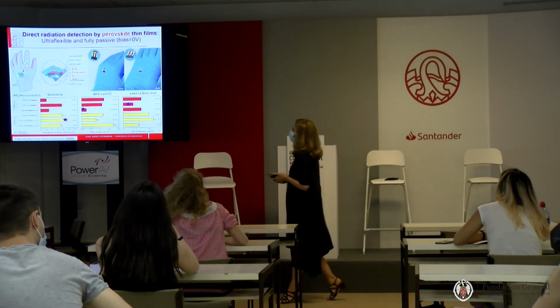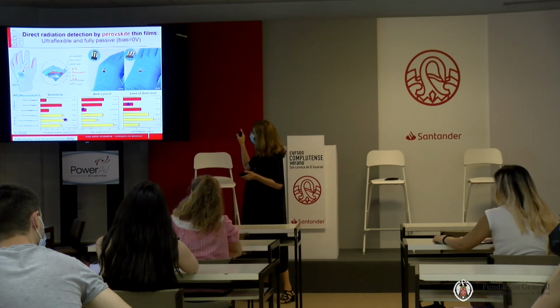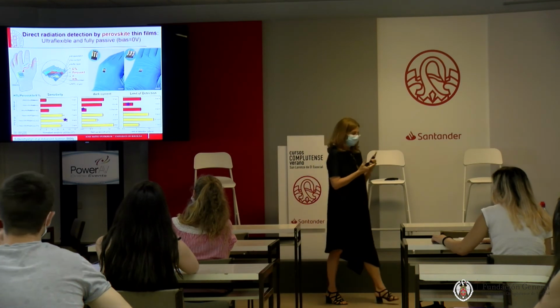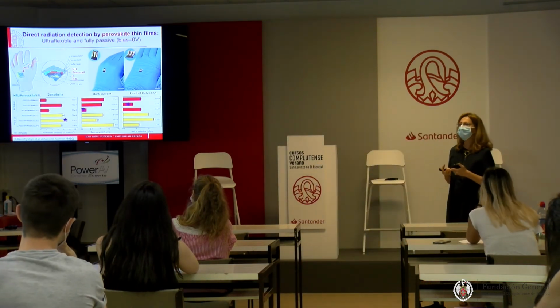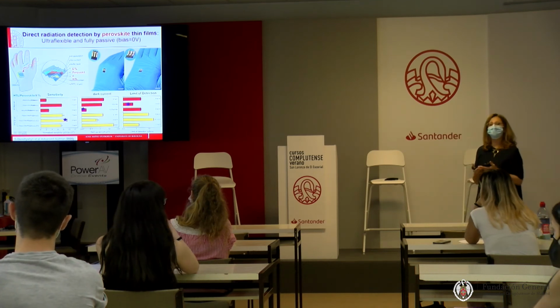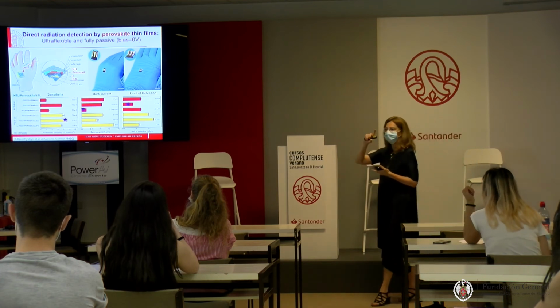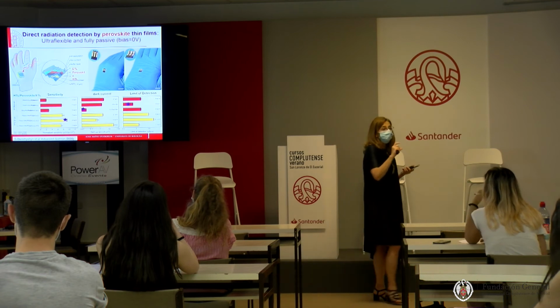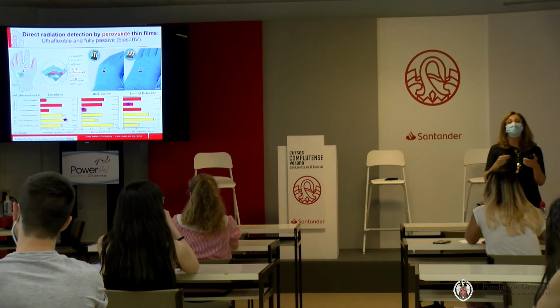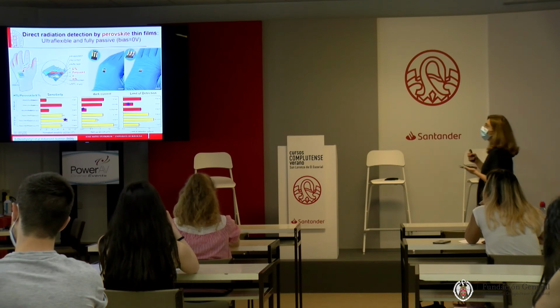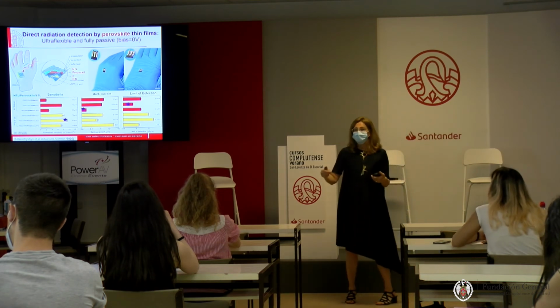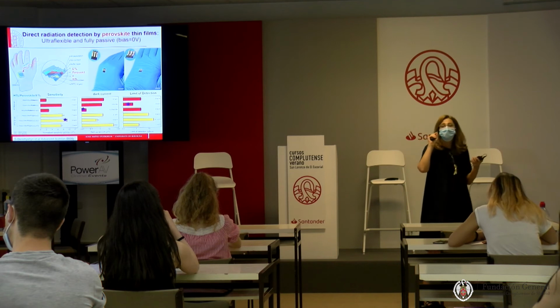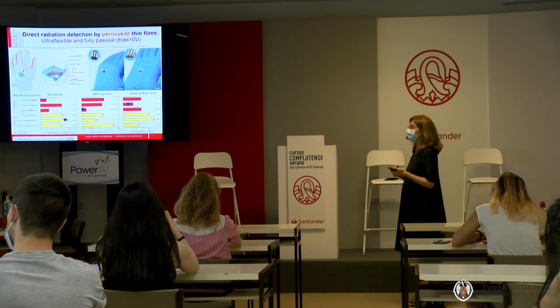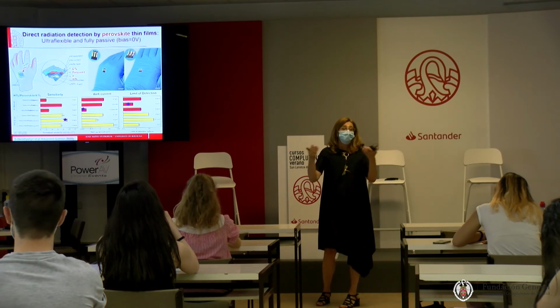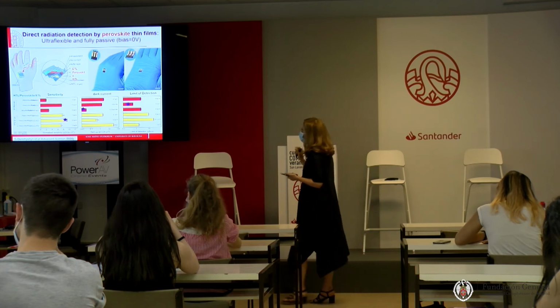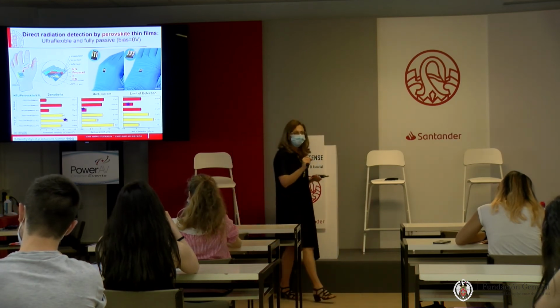What do we get as a response under X-rays? Okay, here you see three different parameters. Sensitivity, we discussed it. And you see added the dark current and the limit of detection, which are the other two important figures of merit of a radiation detector. Sensitivity is the photocurrent as a function of the dose rate. Dark current is, as the name says, the current that you measure without any external stimuli. It has to be very low. Why? Because the lower the dark current, the easier it is to detect every single minor event that occurs. Okay? So the delta I over I becomes bigger if the I is really small. The third is the limit of detection, which is the smallest signal that you can detect.